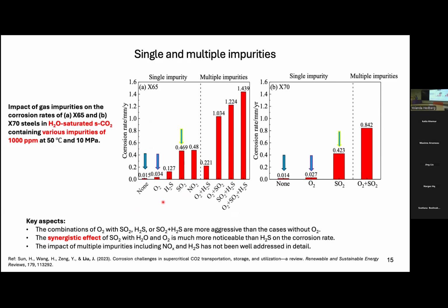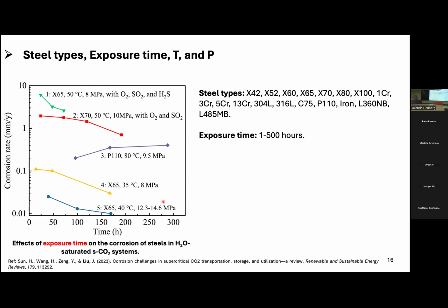But the combination of oxygen with SO2 or other acidic gases is more aggressive, because oxygen can oxidize, for example, SO2 to form a stronger acid, sulfuric acid, right? And for H2S also, oxygen can react with H2S to form SO2 or sulfuric acid. Now, as I said, the impacts of impurities such as NOx and H2S are least studied because of their toxicity properties.